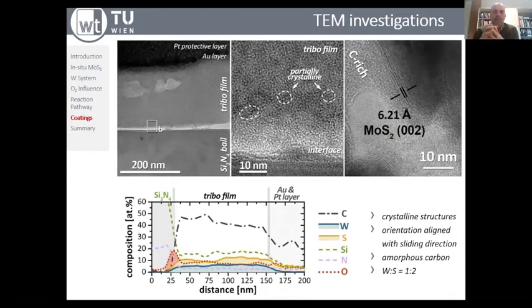actually amorphous. But we can also identify, I hope you can see my mouse cursor, there are some partially crystalline patches forming in this tribofilm. And you can also maybe slightly see these line-like patterns here within these circles. And when you measure the plane distance, the lattice spacing, this corresponds very nicely.